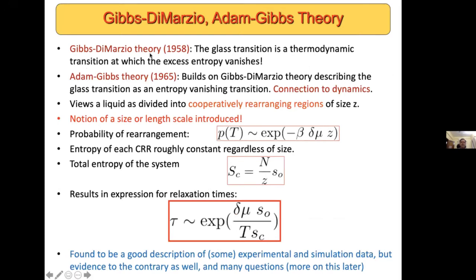So this idea was picked up very early on, one of the earliest theories of the glass transition by Gibbs and DiMarzio in 1958. They developed a theory where the glass transition is indeed a thermodynamic transition at which the excess entropy, or the configurational entropy, as we more generally call it, vanishes. So you have this continuous transition where the excess entropy will vanish at a finite temperature.